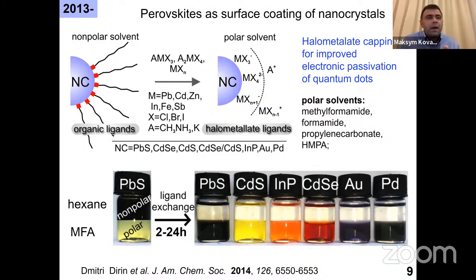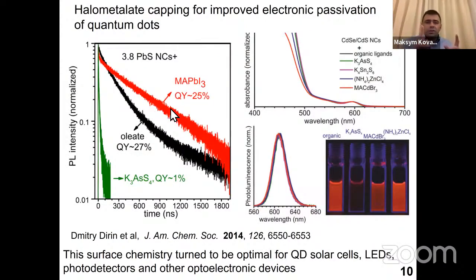And because of that, we could basically fully change the surface functionality from apolar to highly polar, and that you see from the dispersion of these nanocrystals. They migrate from the apolar phase into a polar phase upon this ligand exchange. And what was extremely important back then is to observe that such an exchange can preserve or even improve the electronic state of the surface. So somehow it turned out to be very beneficial to have halides at the surface as compared to chalcogenides, for example.